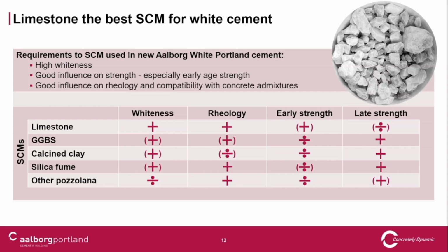But there are obvious disadvantages with some of these. The fly ash is not white, it's dark. Slag, clay and silica fume could be obtained in a white or semi-white quality. But the limestone we're going to use is ultra white—even whiter than our clinker. On the rheology aspect, limestone has a good influence; slag also to some extent; clay does not, the others are okay.